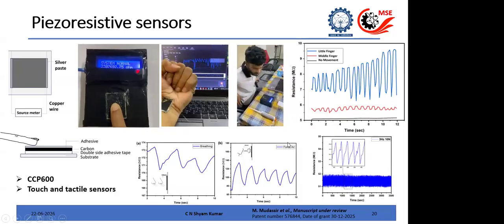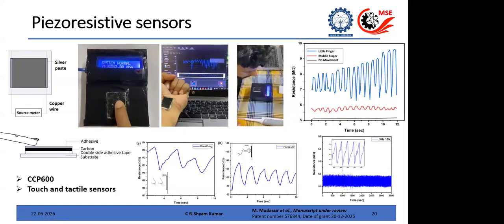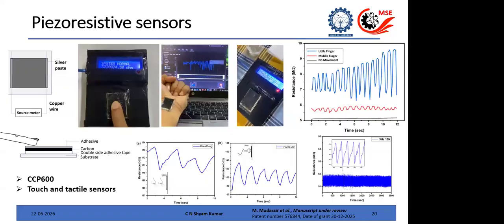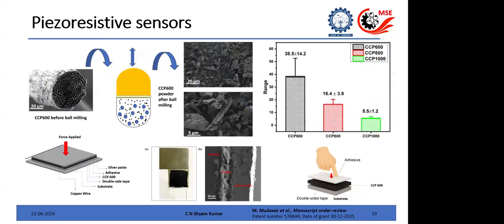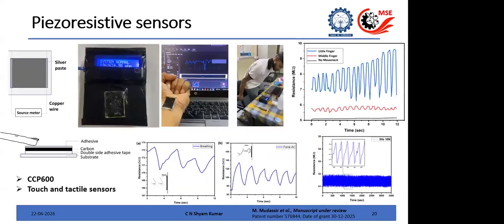So here you can use this powder to make sensors, and you can tune the sensitivity. That is the point. As you can see, you can tune the gauge factor, which is the sensitivity, by changing the pyrolysis temperature. You might not always want a very highly sensitive sensor. So by changing the pyrolysis temperature, you have a change in the piezo-resistive response, and then you can have a sensor with tuned sensitivity.